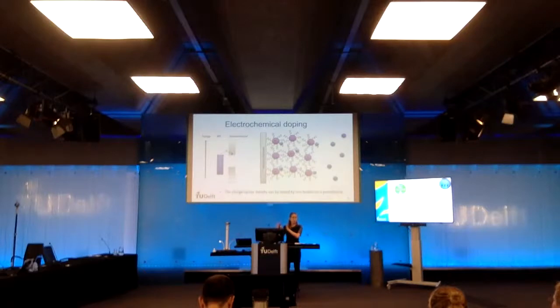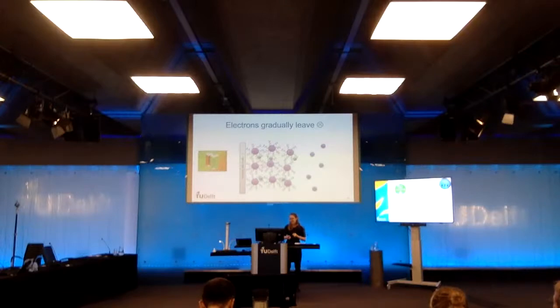And by doing this, we can do this by touching one button on a potentiostat or in a nice software. And we can really tune the conductivity of our semiconductor material by, for example, 12 orders of magnitude. So this is actually quite a simple way to dope our semiconductor materials. And like I said, only with one button on a potentiostat.